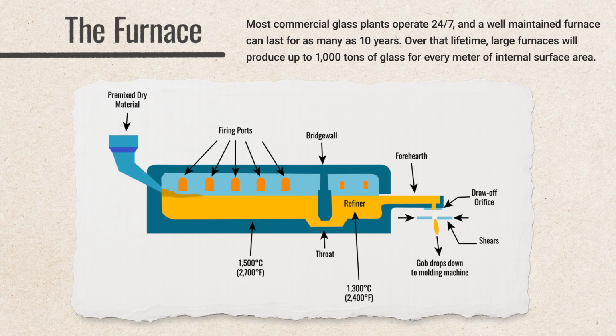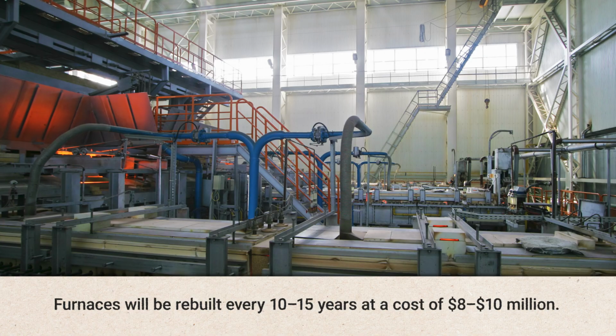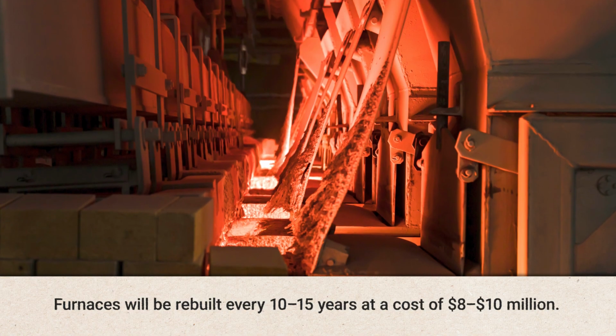Most commercial glass plants operate 24/7, and a well-maintained furnace can last for as many as 10 years. Over that lifetime, large furnaces will produce up to 1,000 tons of glass for every meter of internal surface area. Furnaces will be rebuilt every 10 to 15 years at a cost of $8 to $10 million.